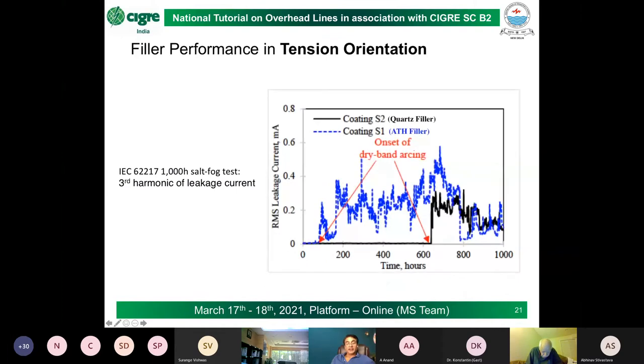But suddenly when you take this same insulator and put it into tension orientation in this 1,000-hour salt fog chamber, what you see is this quartz filler, what we see in S2 here. If you see the bottom of the graph, the black line, this is near dead till well past 600 hours. It's about 640 hours, there is no leakage current. Whereas on the ATH filled coating, the leakage current commences within under 50 hours. So this extra leakage current is really a bad thing.